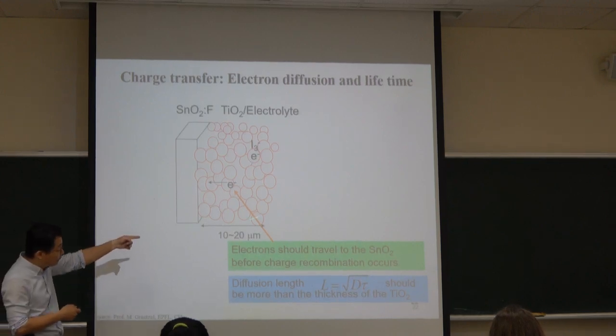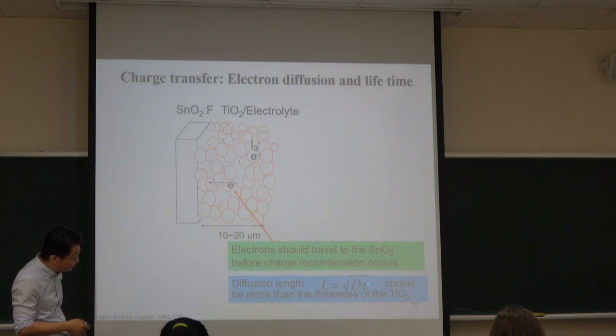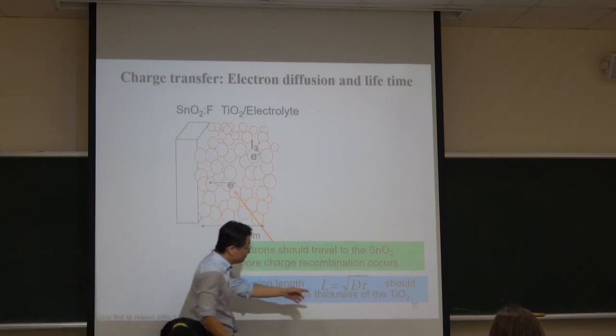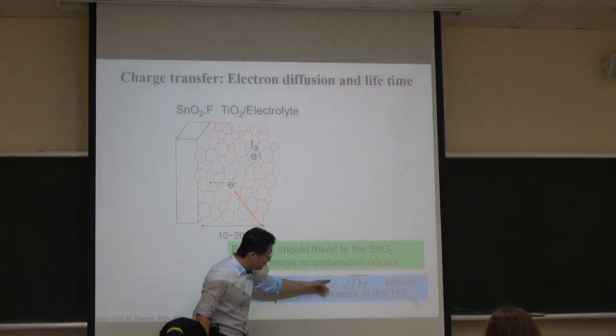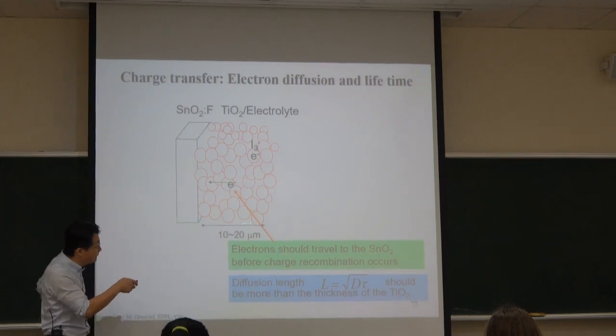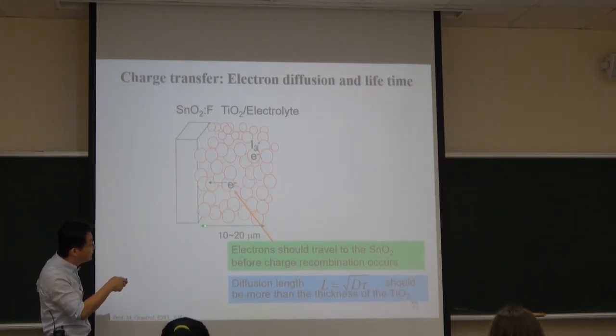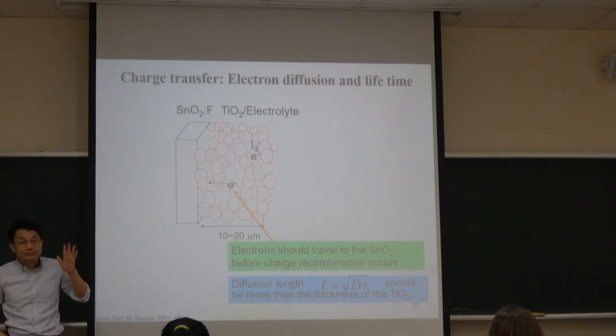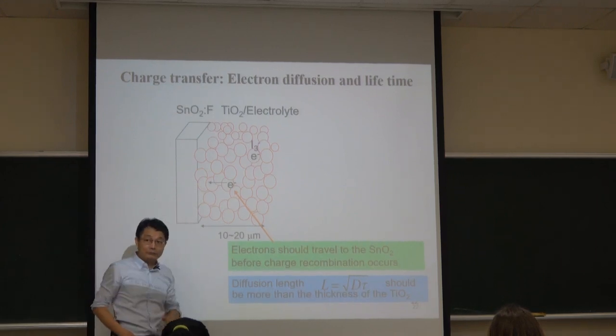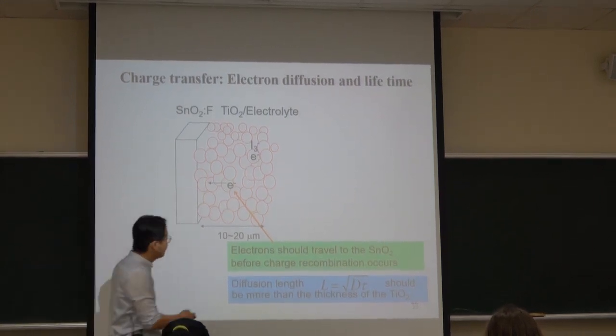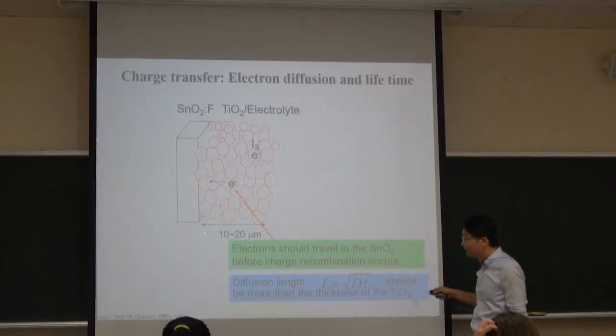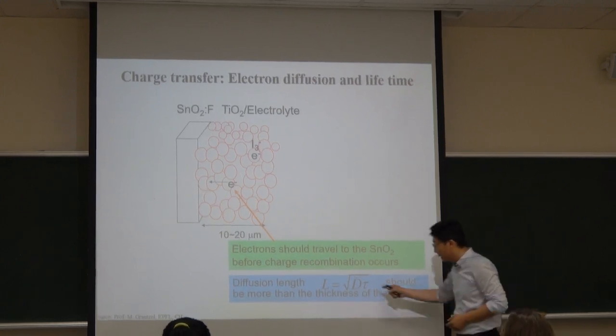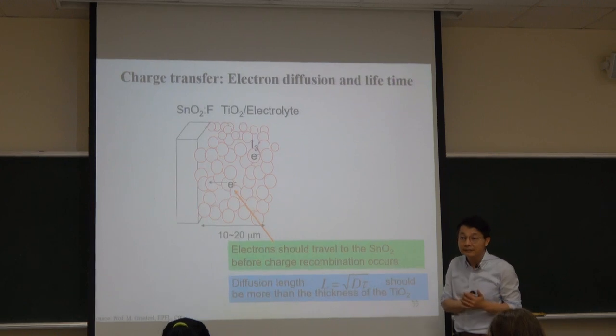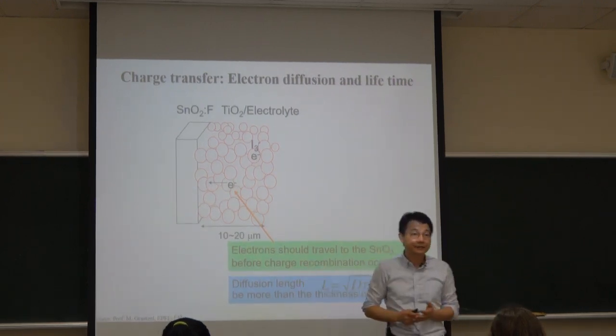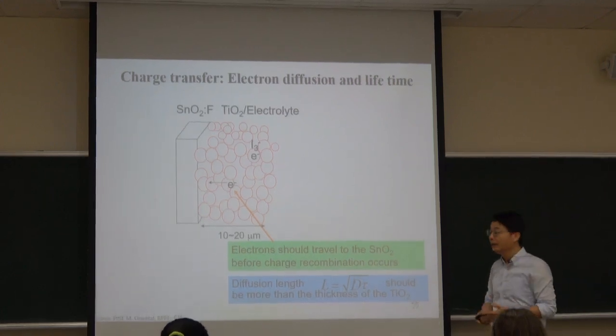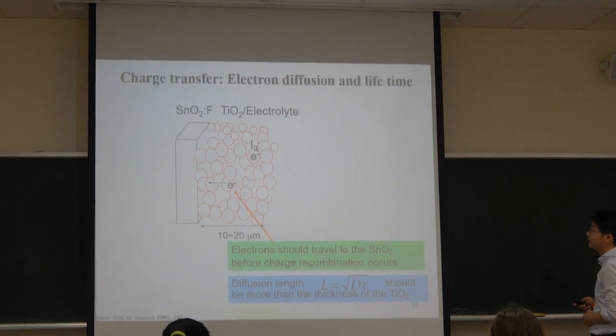No, there is a limitation, the very controlling state I would say, the electron lifetime. Because the electron lifetime determines the diffusion length. This diffusion length determines how thick a TiO2 thin film we should deposit on the conductive glass. Usually it is 10 to 20 micron. This is based on the diffusivity of the TiO2, which you cannot change. This is already fixed. One material has its own diffusivity.